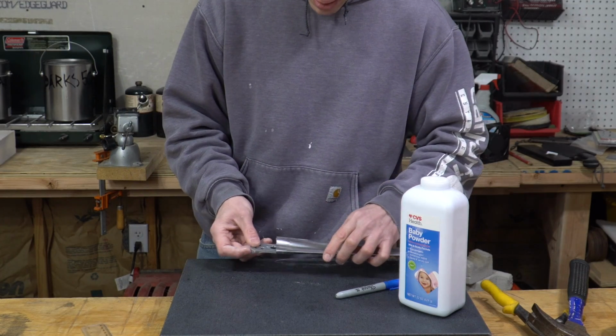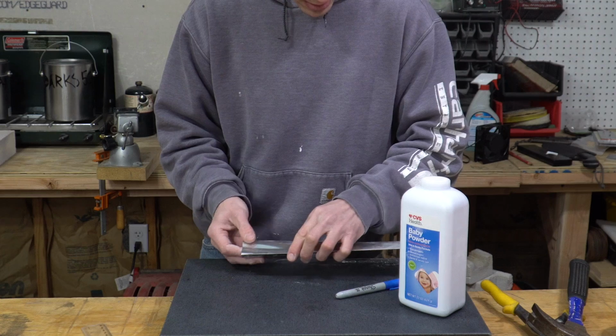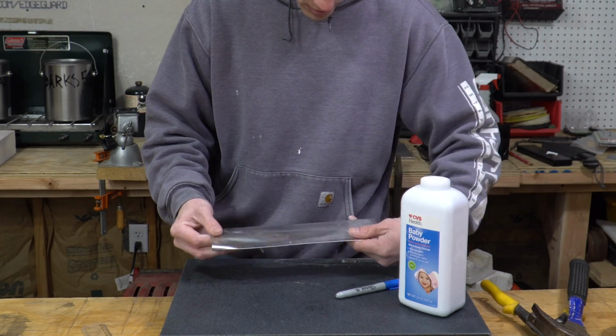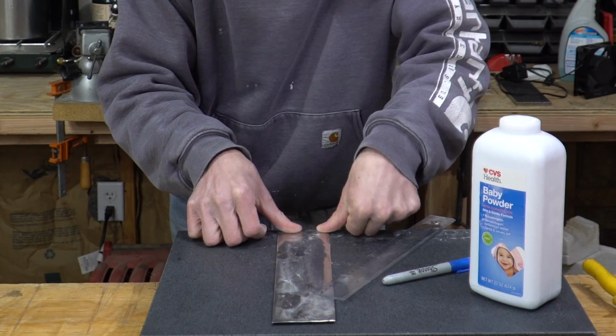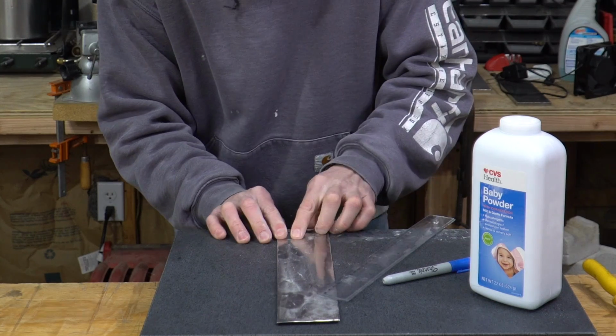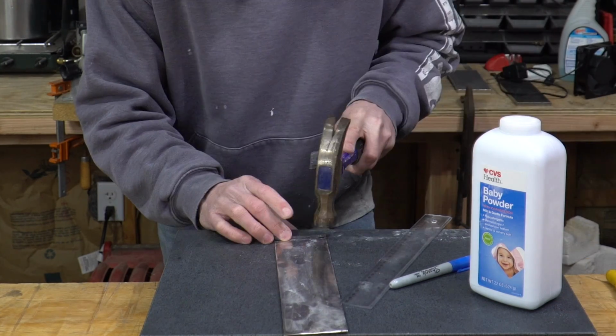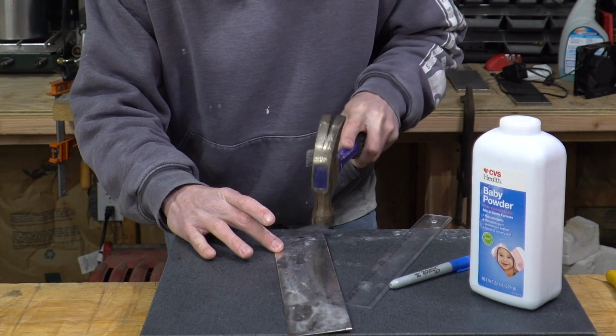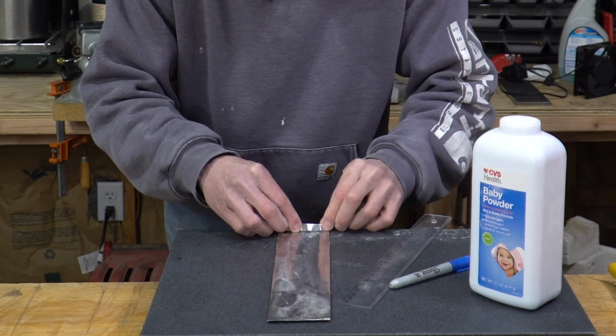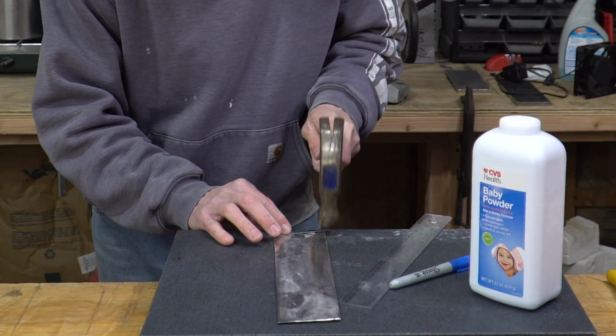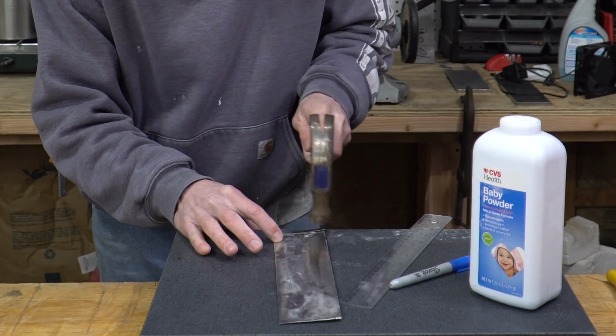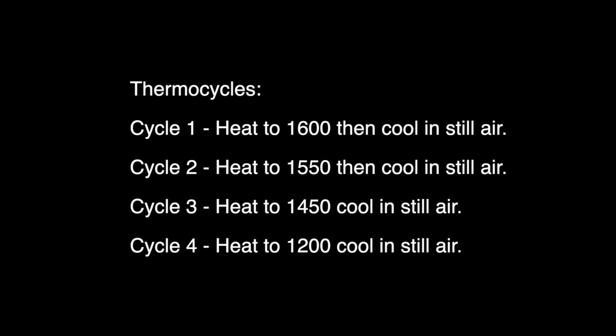At the 1600 degrees we're going to be thermocycling at today, that's not a huge issue. If you are using air hardening steels or going to higher temperatures than what we're using here today, this foil packet welding itself to the steel is a real possibility, and if that happens, it's a real pain to get off.